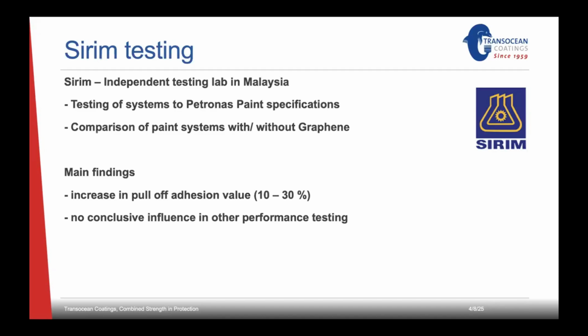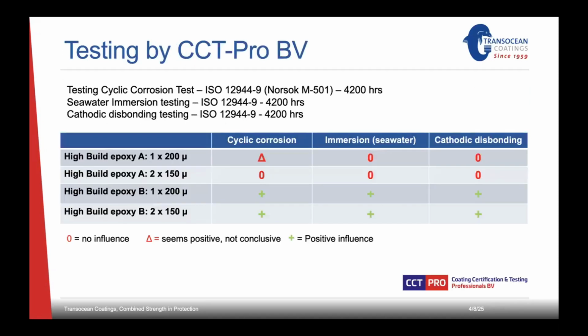We also did testing in the Netherlands, by the testing company CCT Pro. There we did more stringent testing. We tested against ISO 12944 and NORSOK M501. We ran the cyclic corrosion test for 4,200 hours. We did the seawater immersion testing and also the cathodic disbonding testing, all for 4,200 hours.